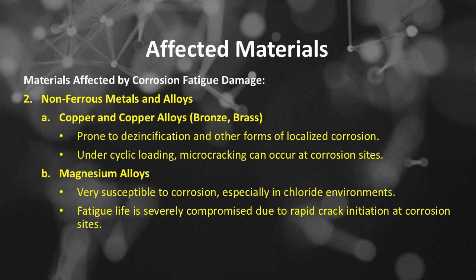Number 2 of materials affected by corrosion fatigue damage is nonferrous metals and alloys, which includes: number A, copper and copper alloys, bronze, brass, prone to dezincification and other forms of localized corrosion. Under cyclic loading, microcracking can occur at corrosion sites. Number B, magnesium alloys, very susceptible to corrosion, especially in chloride environments. Fatigue life is severely compromised due to rapid crack initiation at corrosion sites.